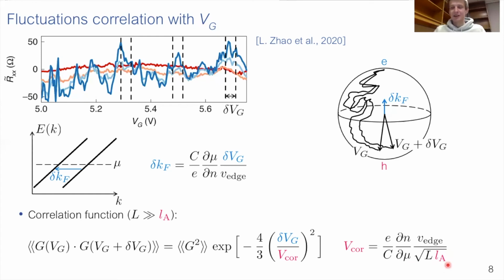You see, the Andreev length is sort of a degree of disorder. If we perform a thought experiment in which we increase the degree of disorder in superconductors, then the Andreev length would go down. So essentially, switching between electrons and holes would happen quicker. So the Andreev length goes down, but the correlation radius increases. So we increase the amount of disorder, but the signal gets smoother.